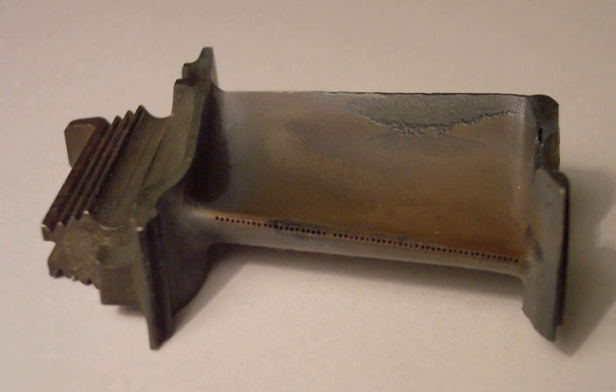In most applications, the bond coat is either a MCrAlY, where M equals Ni or NiCo, or a Pt-modified aluminide coating. A dense bond coat is required to provide protection of the superalloy substrate from oxidation and hot corrosion attack, and to form an adherent, slow-growing TGO on its surface. The TGO is formed by oxidation of the aluminum that is contained in the bond coat.